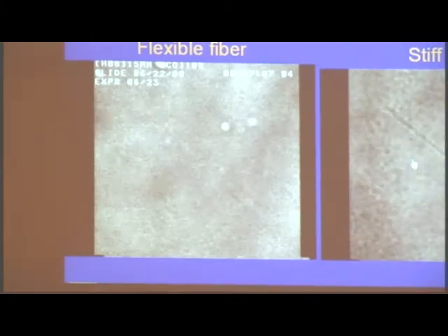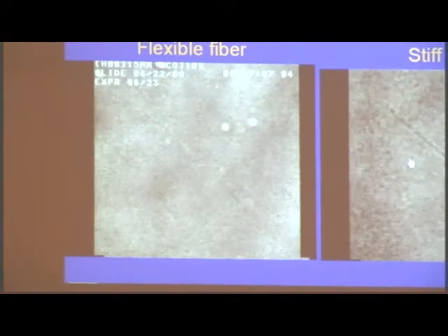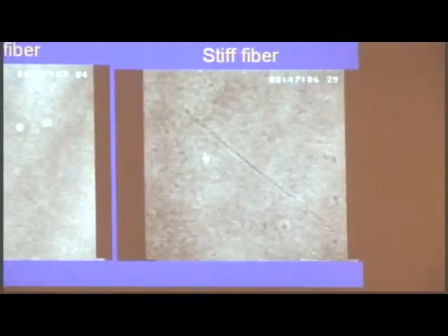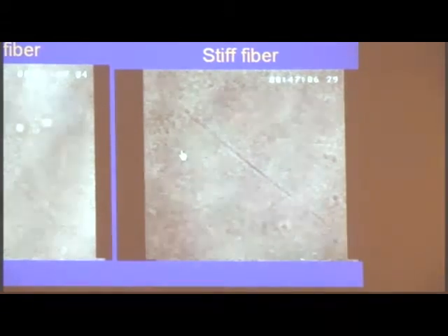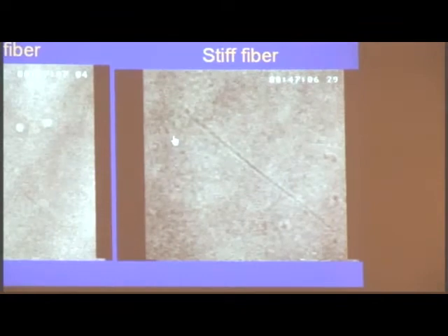It's 1/10 as stiff as structural proteins such as actin and tubulin, but it's 1,000 times more stiff than proteins such as elastin, which are in the connective tissue and so forth, which is also a structural protein. So for a protein that's soluble, in principle, this is quite extraordinary, that you can make such a stiff fiber.